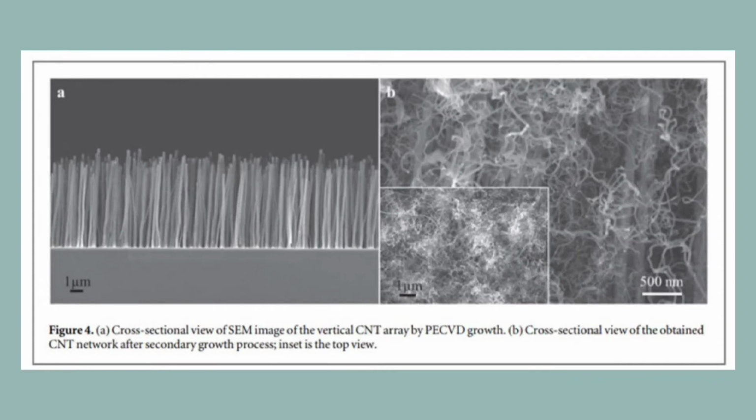Figure 4a shows SEM images of CNTs obtained from PECVD growth. They are well aligned vertically into an array. These CNTs have fairly uniform diameters around 150 nm. The length of the CNTs is around 7 micrometers, with slight differences among them. Image processing of several top-view SEM images of the CNT array was used to measure the surface area fraction of the CNTs, and then the volume fraction of the CNTs was estimated. The average volume fraction of CNTs is calculated to be about 10%.